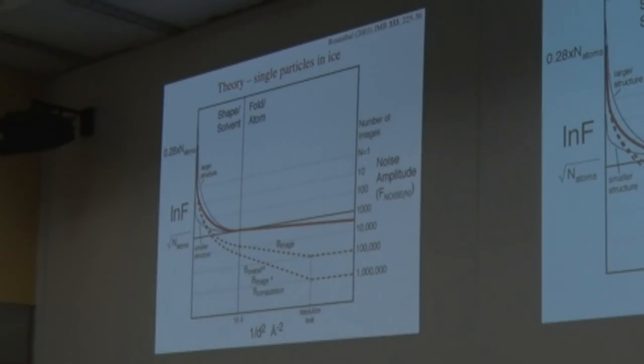When we were doing this in 2003, the images weren't very good, so the results were worse than that. They were blurry, there was charging, there was motion, and in the computer you're not determining the angles very well. So the dotted lines indicate practically imperfect versions of what you hope to get one day when you've fixed everything. And in 2003, the point where the signal reaches the noise level tells you your resolution. Beyond that, you've still got data, but it's under the noise level and you can't see it. At lower resolution, you see it. So that was the resolution line.